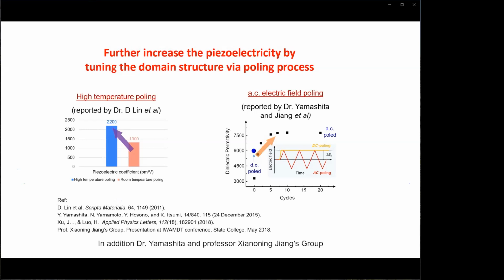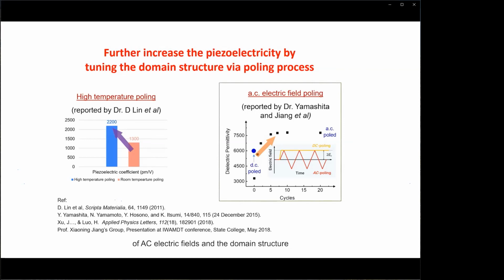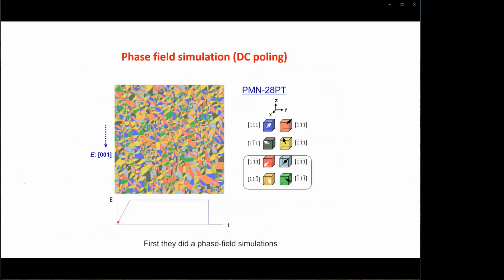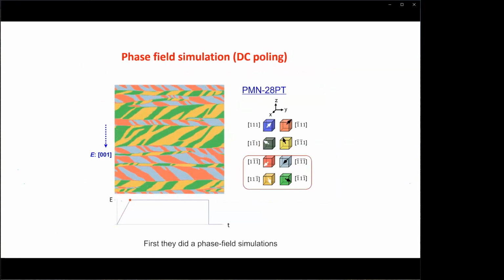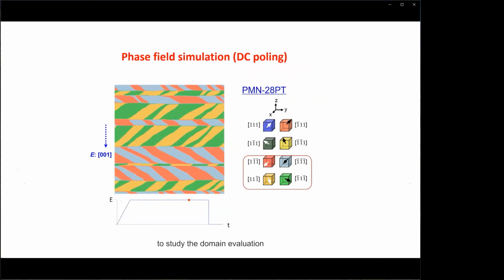In addition, Dr. Yamashita and Professor Xiaoning Jiang's group reported that the piezoelectricity can be enhanced by using an AC electric field to pole the crystals. Today, I will focus on the effect of AC electric fields on the domain structure, where we can see some very interesting phenomena. First, we did phase field simulations to study the domain evolution during traditional DC poling and also AC poling.